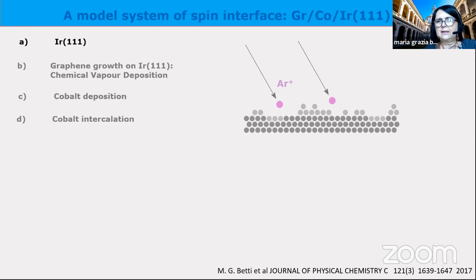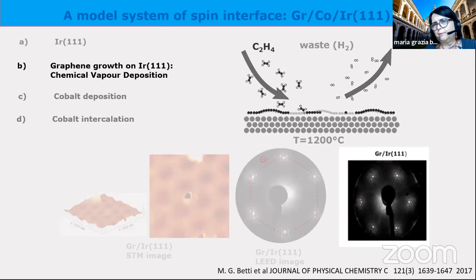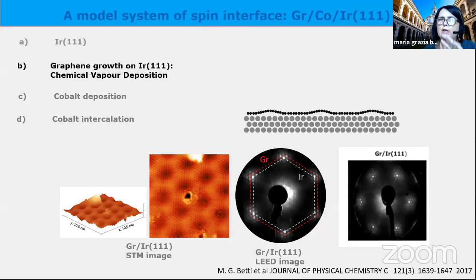Then I will show you very briefly how, because it's a model system of spin interface, but it's not so easy to build up. Then we make graphene. It's easy to make graphene on iridium. You will have a corrugated layer of graphene with a moire superstructure, and you can see on the left, in the direct space, an STM image, and in the reciprocal space, a LEED image of this corrugation.